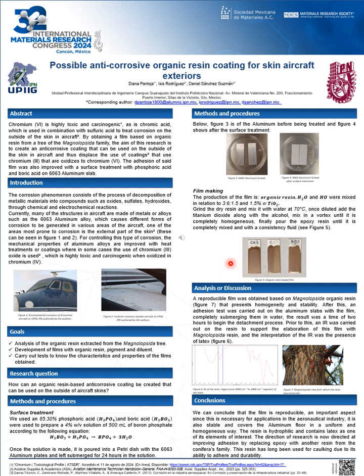Analysis or discussion. A reproducible film based on Magnolopsida organic resin was obtained, since the experiment was repeated several times, and the same film was obtained. This film presents homogeneity and stability. After this, an adhesion test was carried out on the aluminum slabs with the film, completely submerging them in water. The result was a time of 2 hours to begin the detachment process.